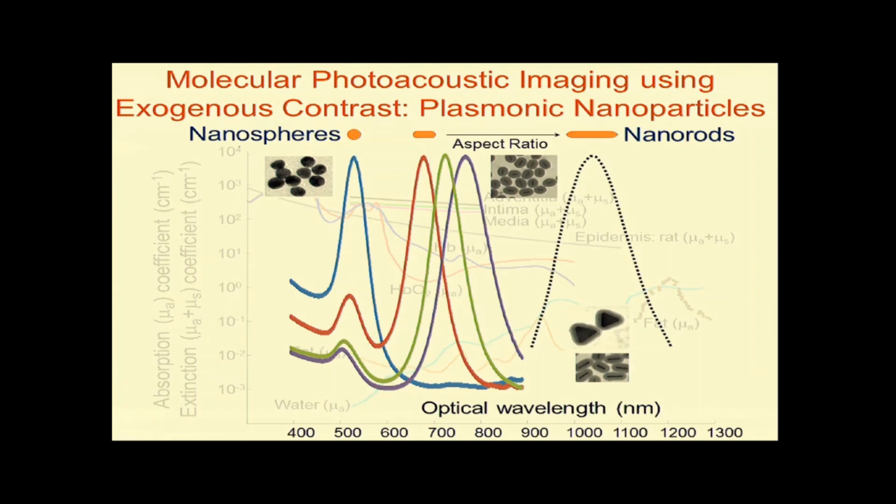And with dyes, that's extremely difficult to do. The dyes will kind of stop at 750, maybe 800 nanometer absorption, whereas with nanoparticles, if I make them anisotropic or play some games in terms of composition of those constructs, I can actually make them absorb at 1064 and even slightly higher. Right, so that's one property of nanoparticles that's not duplicated by dyes.